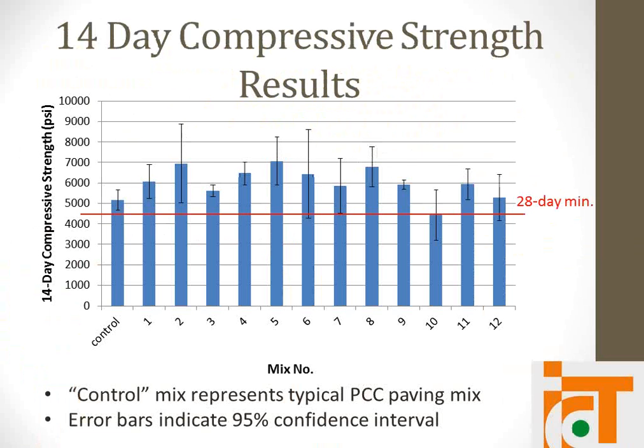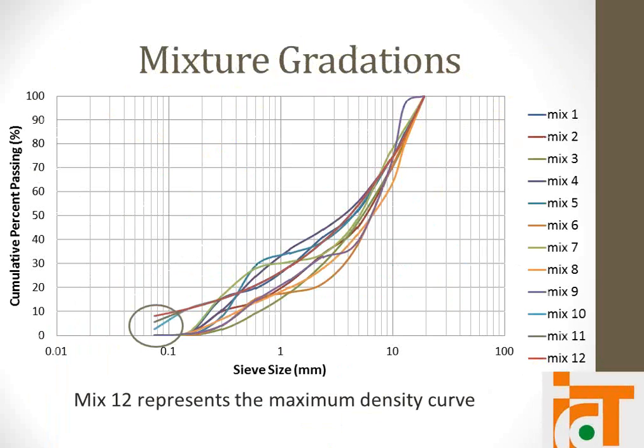Yeah. So 1 through 12, the only difference between them is their gradation. They have the same cement content. They have relatively the same optimum moisture. For all 12 mixes tested, it ranged from 6 to 7.1. So it was a very narrow range of optimum moisture, but it was the same aggregate materials.